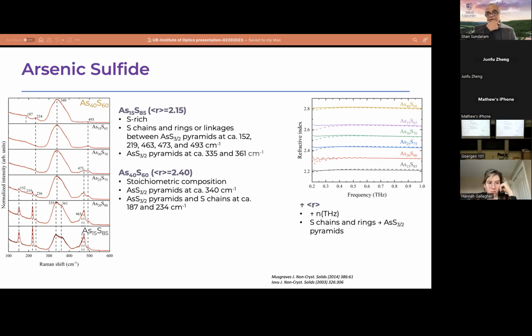So here, in the next couple of slides, I will show you once again the Raman band of the chalcogenide glasses right next to the terahertz refractive index property we have measured. Once again, you will see we are able to map the various bands we see, and we are able to also compare various compositions with various R values. That means the coordination number is changing when I'm changing the chemistry of the glass.